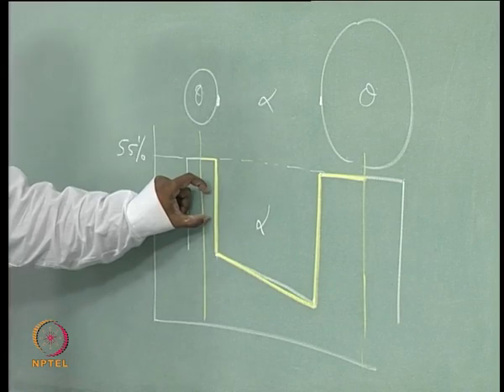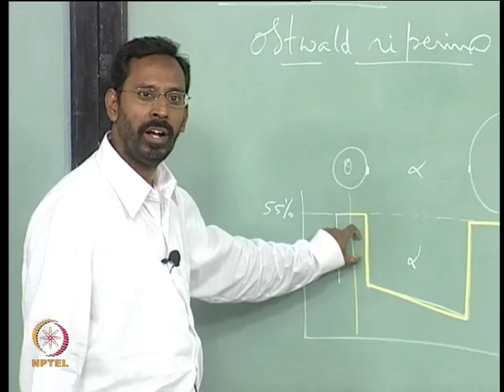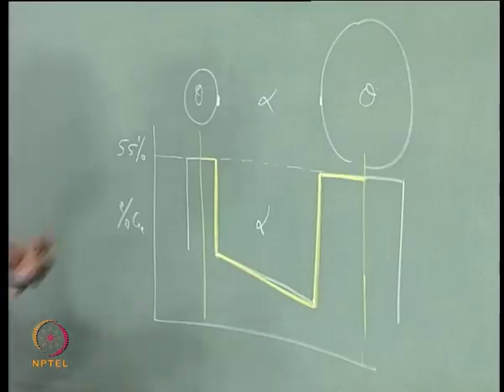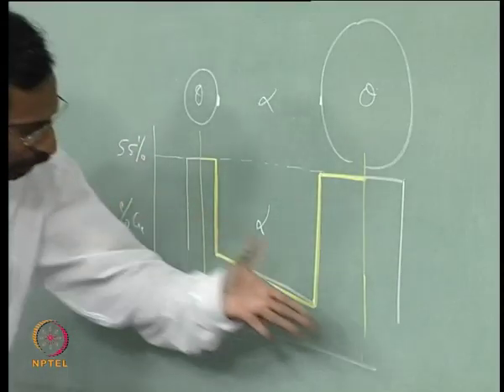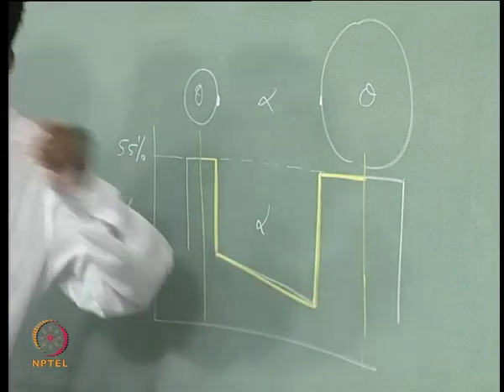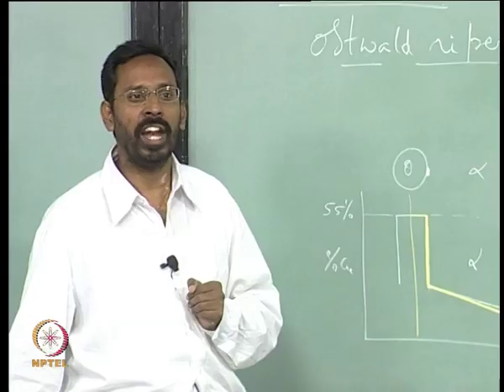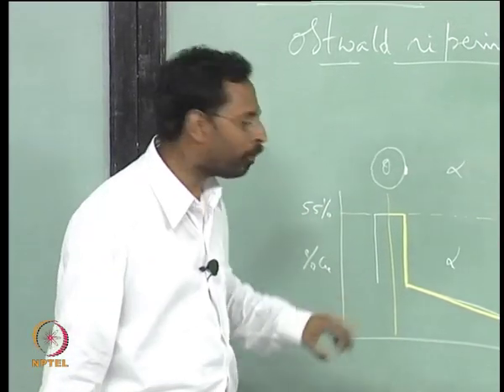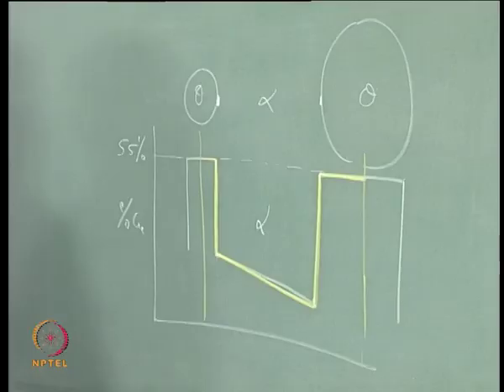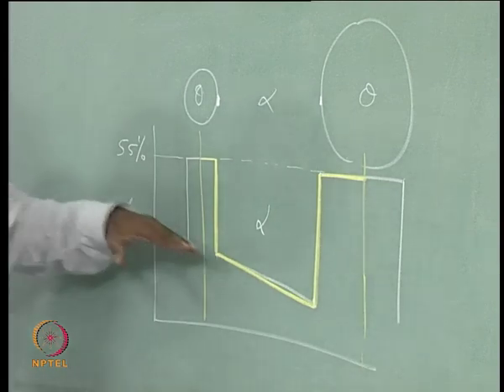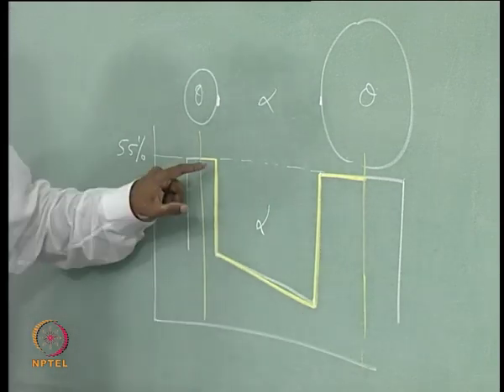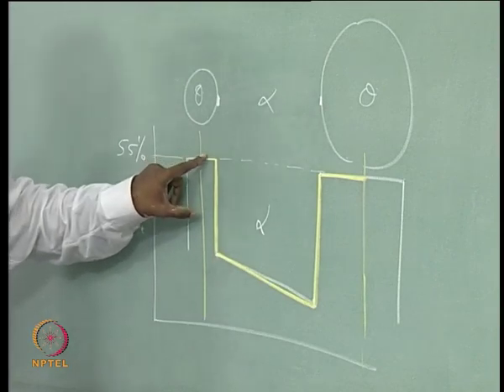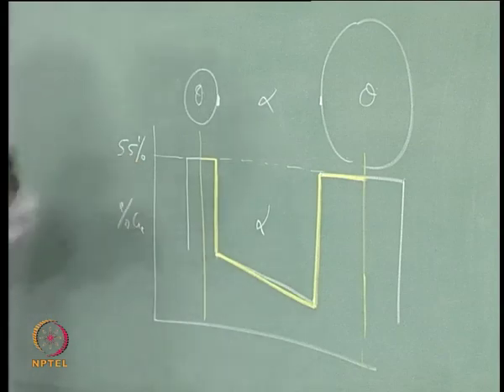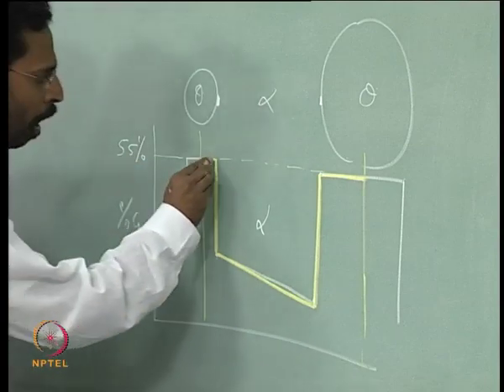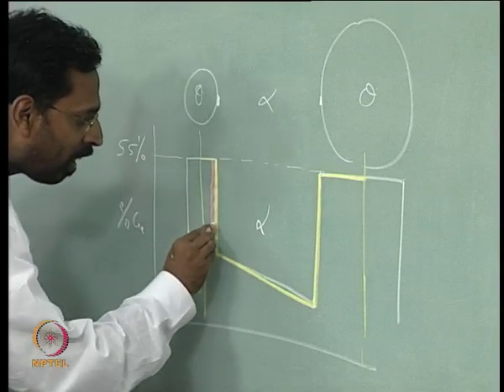You see that copper atoms which are here want to diffuse towards this, but you need a constant supply of copper atoms for the copper atoms to go down this particular decreasing concentration gradient. Where are the copper atoms coming from? The copper atoms come from this particular particle. The smaller particle provides the reservoir of copper atoms, so that the copper atoms start moving in this direction, because the theta has a higher copper content. So, this theta rejects some copper atoms by dissolving by a small amount, a small delta x of this theta.